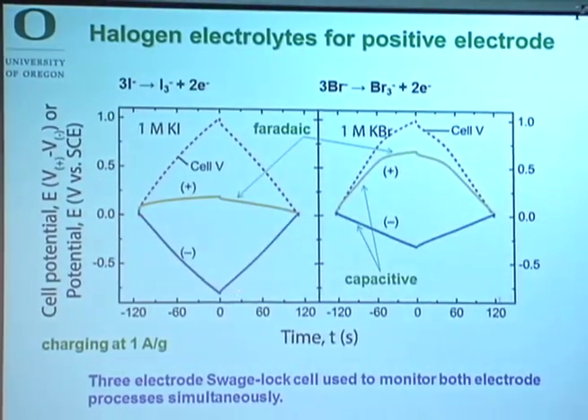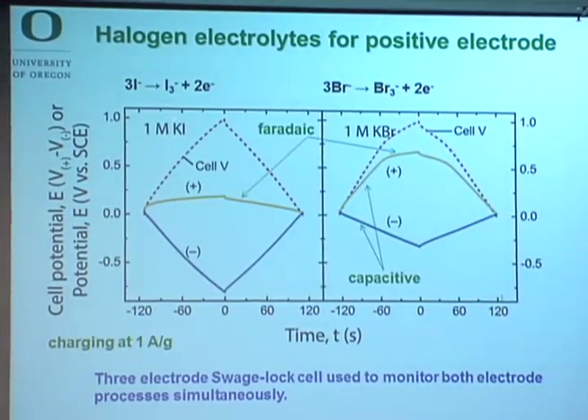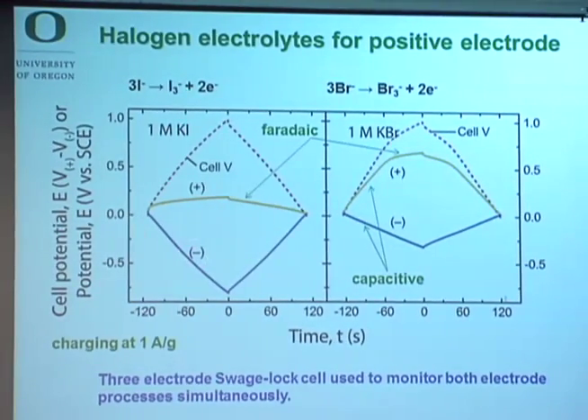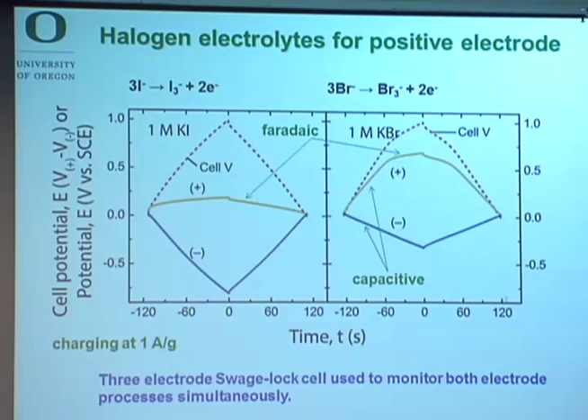On the negative electrode, however, you see that its potential changes linearly with time, because the potassium ions that migrate to the negative electrode build up in a double layer, and you can't transfer charge to them. So it's a purely capacitive mechanism. If you do the same experiment with bromine, you see similar results, except now bromine has a much more positive formal potential. So you see both a capacitive charging regime and a rollover where you start doing the Faradaic charging of the bromine. That makes perfect sense based on classical electrochemistry.